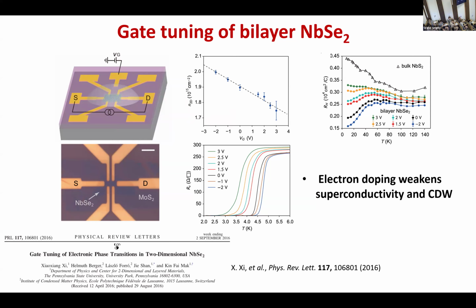Earlier, a long time back, there were some observations that selenium could easily escape from the niobium diselenide surface. Selenium atoms could create vacancies. Is it possible that this can be a mechanism for the electron doping, and this disorder of selenium adds to the suppression? That could be. I think in their paper, they're trying to claim this is electrostatic by showing that the scaling effect is kind of linear, and also it's reversible. If you really dissolve selenium, then it's not reversible.